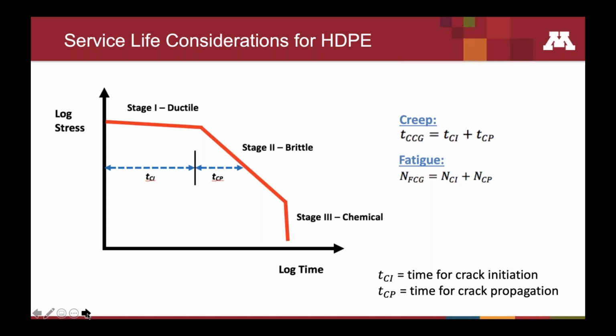Now, some technical slides. There's a couple of interesting components with regards to polyethylene specifically. Polyethylene experiences 3 stages of failure: stage 1, 2, and 3. Stage 1 failures are ductile in nature. Those are under very, very high stresses. We can see that we're at log stress on the y-axis and log time on the x-axis. Generally, for these types of pipes that we're dealing with, we don't see any stage 1 failures because these are non-pressure pipes under low stress.